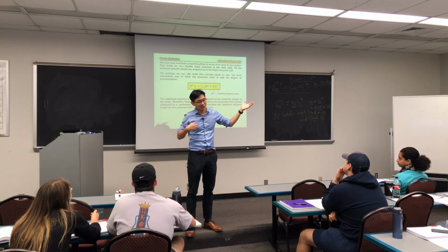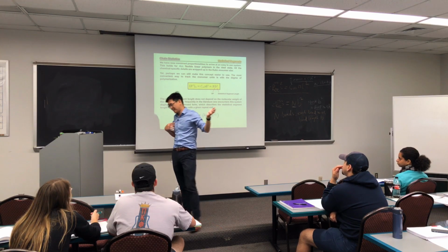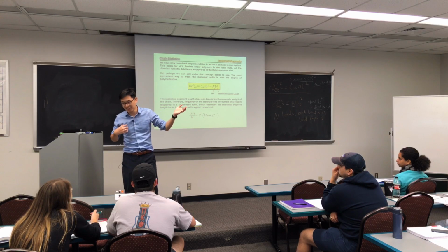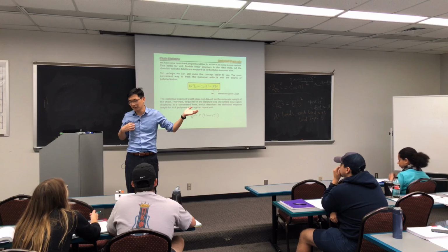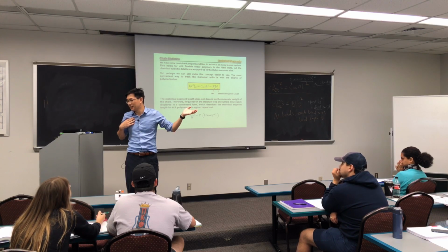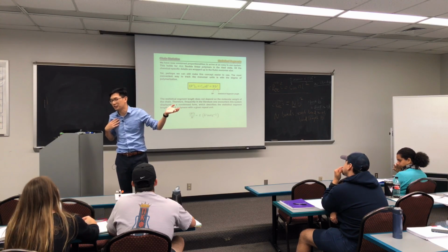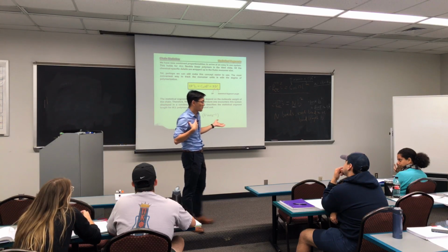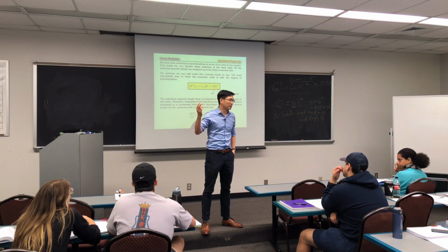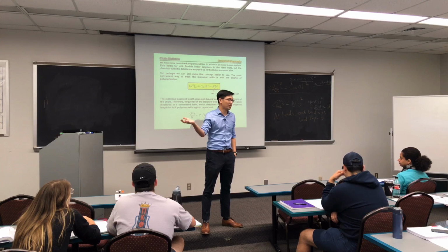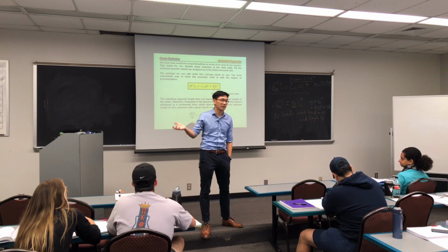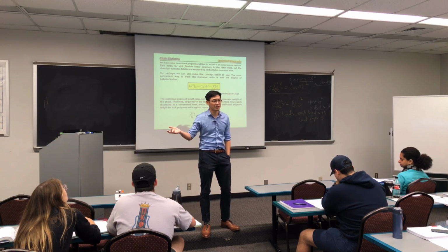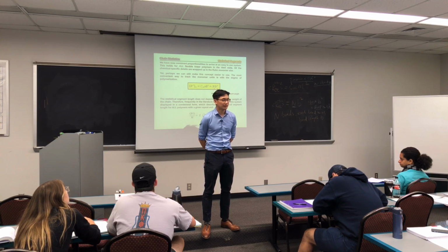Or you could be someone trying to take an easy route, or being smart, where you just count the degree of polymerization, which you can easily get from molecular weight divided by segment molecular weight. And if you know what its b value is, you can just apply a freely jointed chain, and N b squared will give you the final value of the chain dimension. And they would behave almost the same. Does it make sense for everybody?